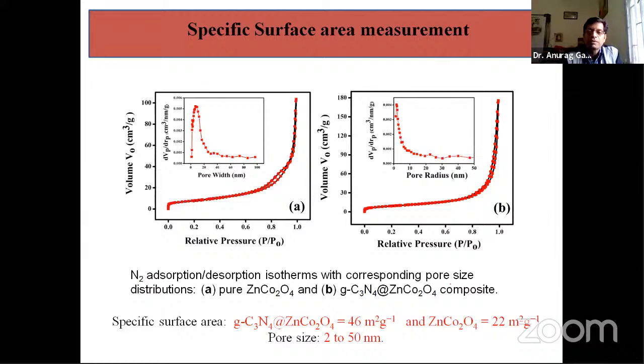In this method we found that the surface area is around 46 meters squared per gram, meaning 1 gram of material could be spread up to 46 meters squared. And the pore size is 2 to 50 nanometers. Pore size is also very important in energy storage materials, because the electrolyte ions, once they move, will enter into the pores. How many ions enter into the pores and how long they stay in the pores affects the performance of your energy storage device. So we use a pore size of 2 to 50 nanometers. This is called the mesoporous range. There are three types: microporous, less than 2 nanometers; mesoporous, 2 to 50 nanometers; and macroporous, 50 nanometers and above. The optimized pore size for these materials is 2 to 50 nanometers.